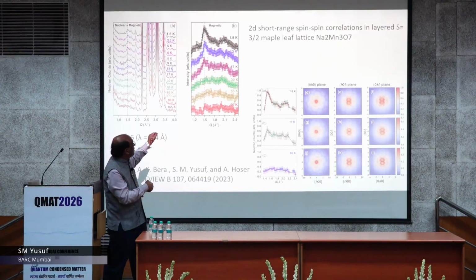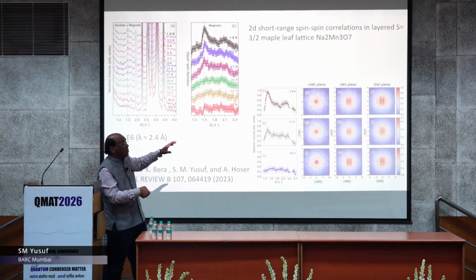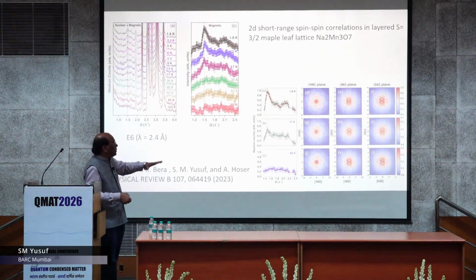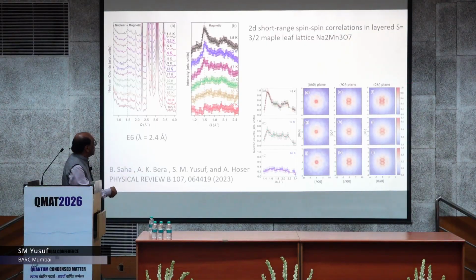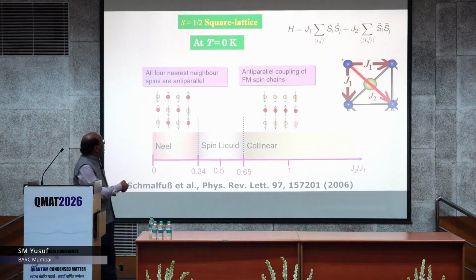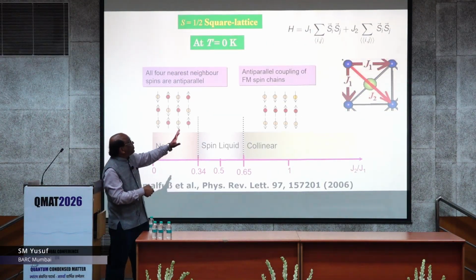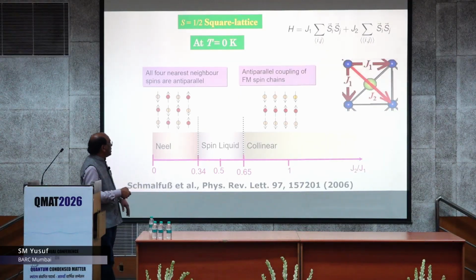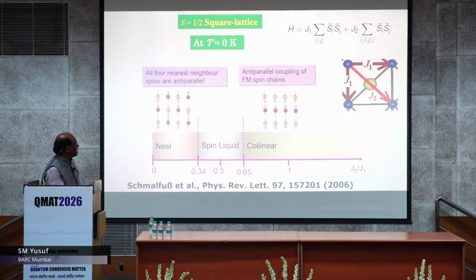If there is a sharp Bragg peak, then these will be dots. So it is an H0L plane; we have mapped how the magnetic correlation is there. Now I move from triangle to square lattice. In square lattice we have worked a lot, and this is the theoretical phase diagram.